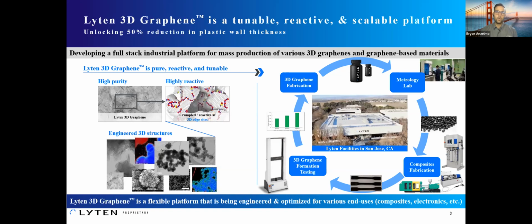But what we've done here is really synthesize the material from a hydrocarbon source, and then we refer to it as a nano assembly. So actually at the molecular level, modify and manipulate the atoms to arrange in an orientation or a pattern that you can see here on the bottom left, just a few of those structures. Again, the engineered 3D structure really is architected and designed for an end application. It's a highly pure system. So there's 4 nines pure or higher of graphene content.